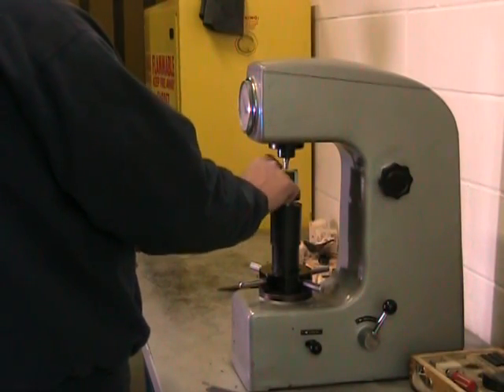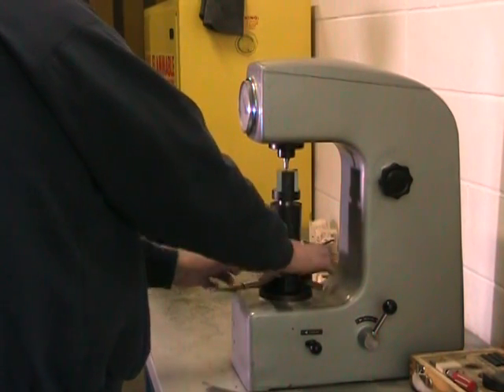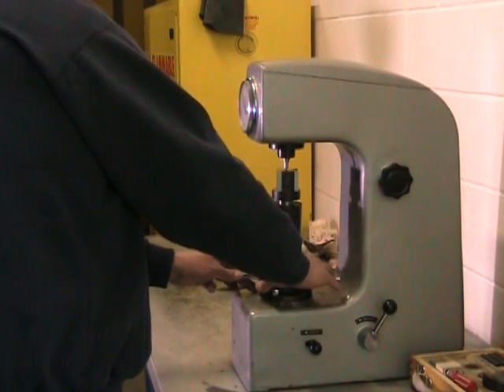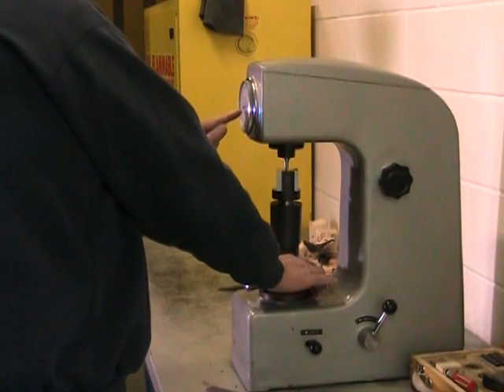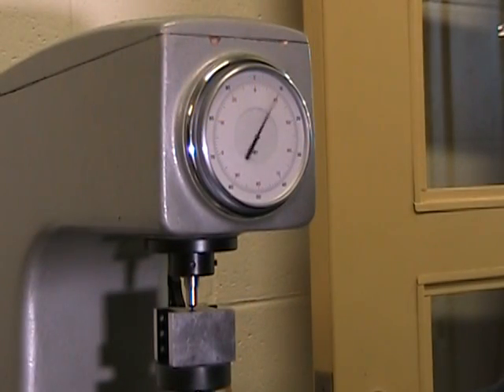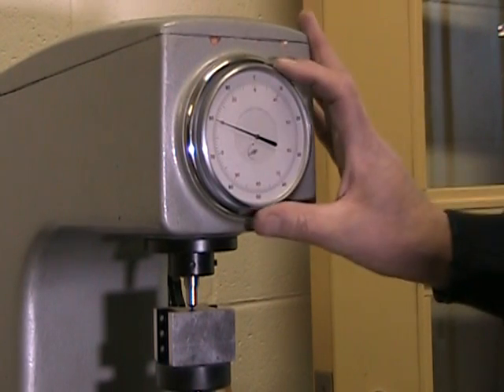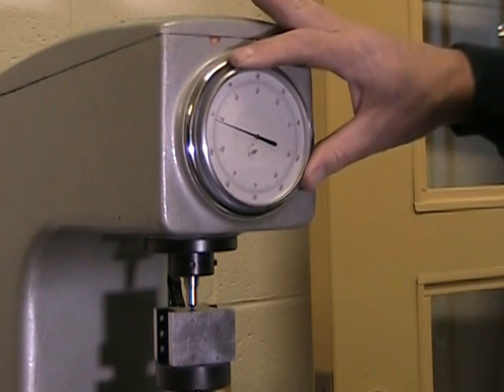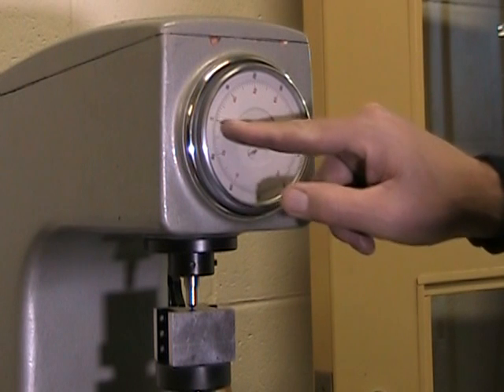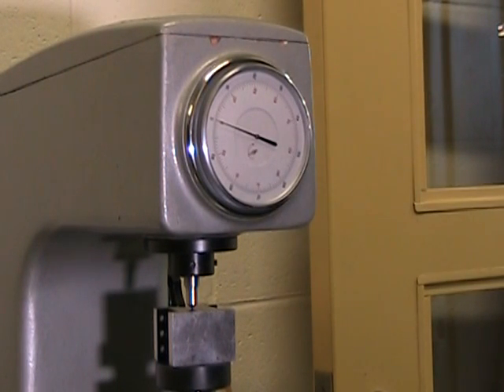Now we're going to bring the part in contact with the diamond by using the hand wheel. The 10 kilogram preload is very important because it levels the playing field and makes sure that all tests are performed with the same starting point. Once the small dial indicates that we have the proper preload, we can set the main scale, in this case the C scale, to zero.